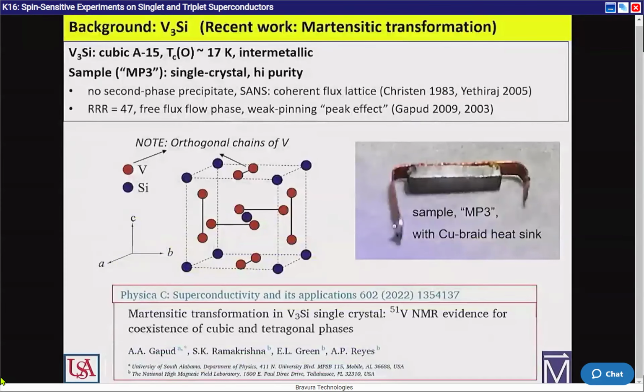Just like niobium tin, we have an A15 superconductor, but instead of niobium chains, we have vanadium chains in orthogonal directions. It's a nice orthogonal mesh of chains. TC of 17 Kelvin. A very durable intermetallic alloy. It's been around since 1983 and has yielded many studies over the years for different groups, including our latest work on studying the martensitic transformation using NMR, as described in our recent paper.